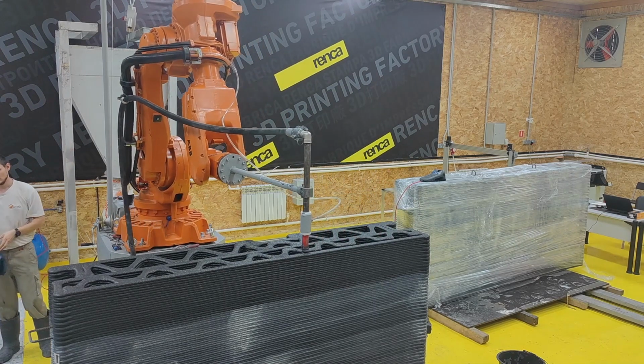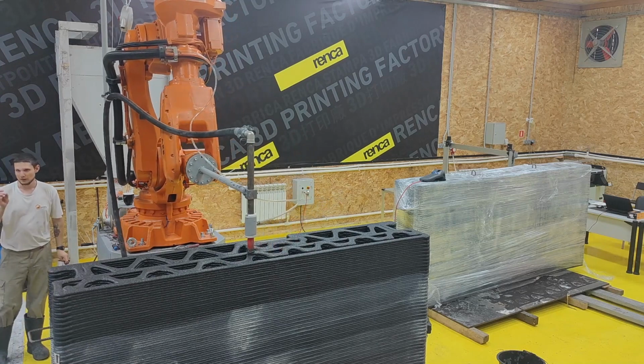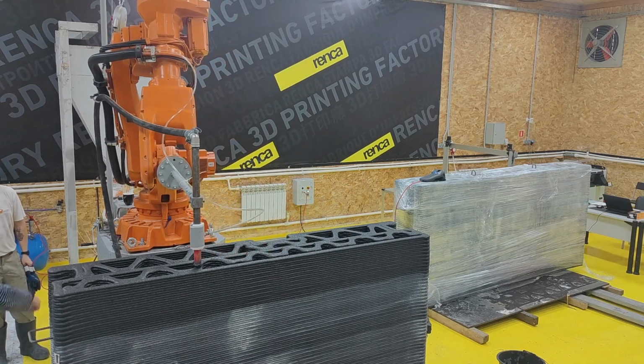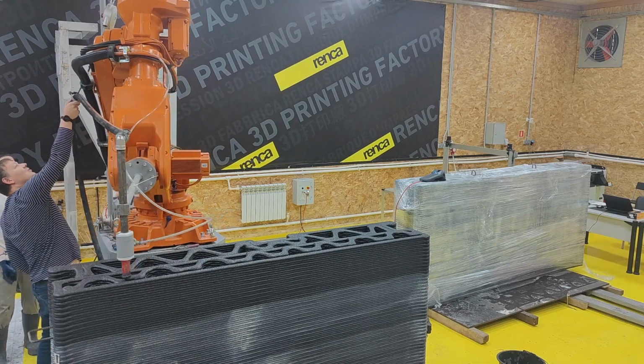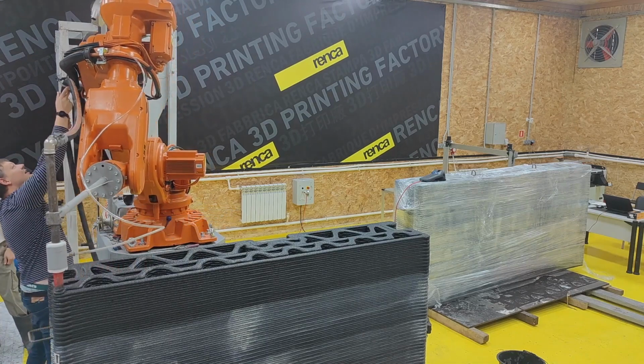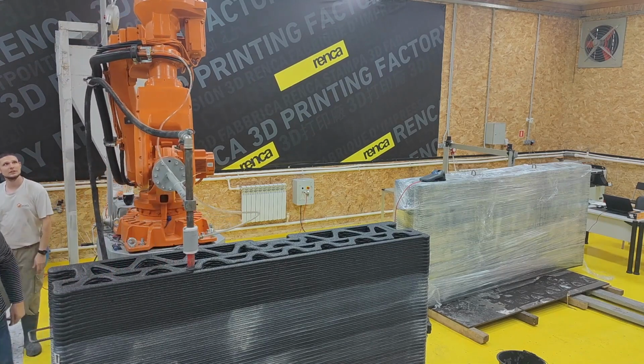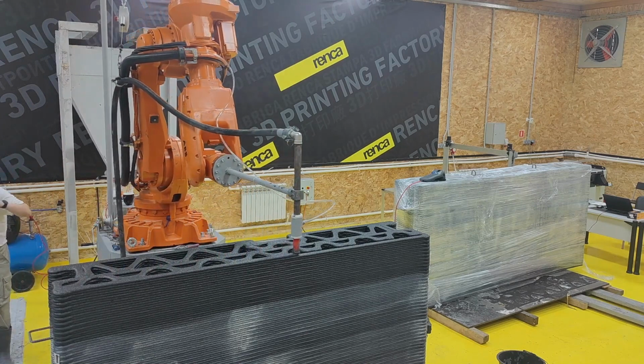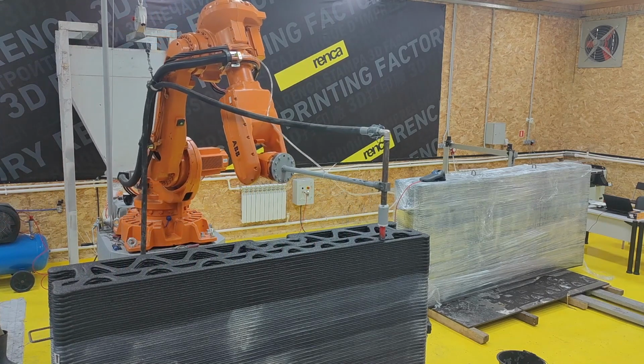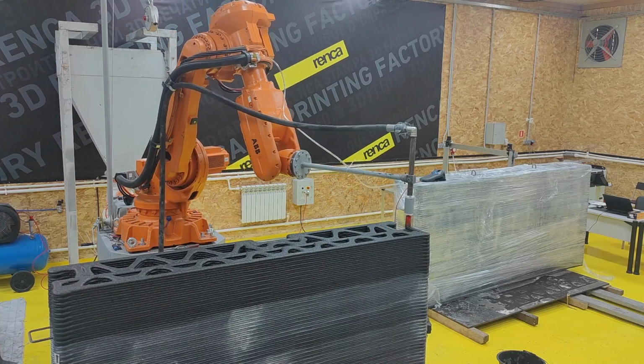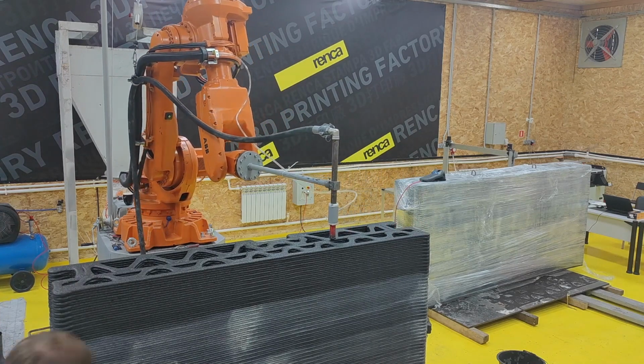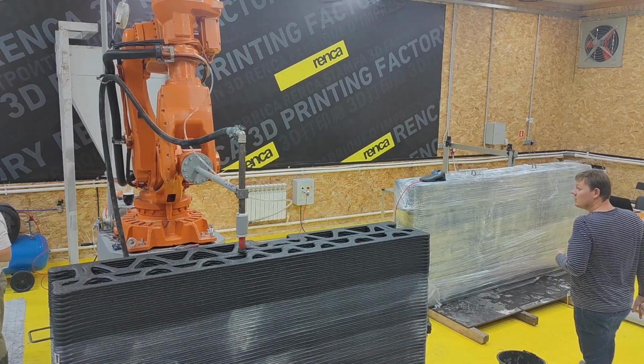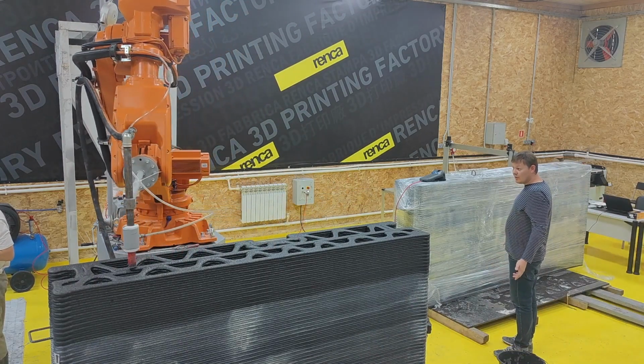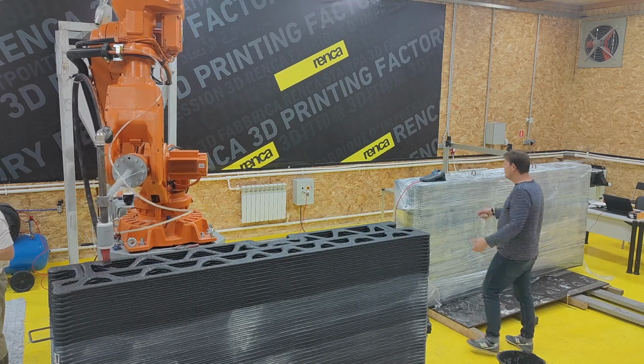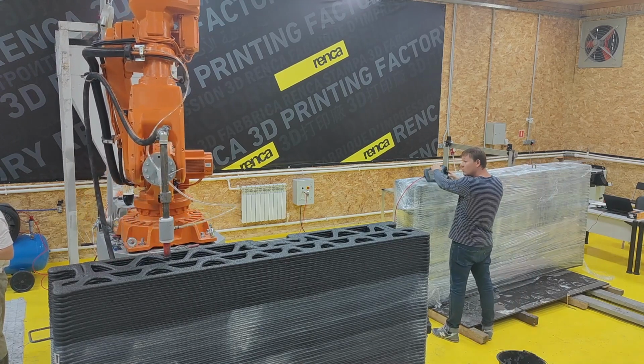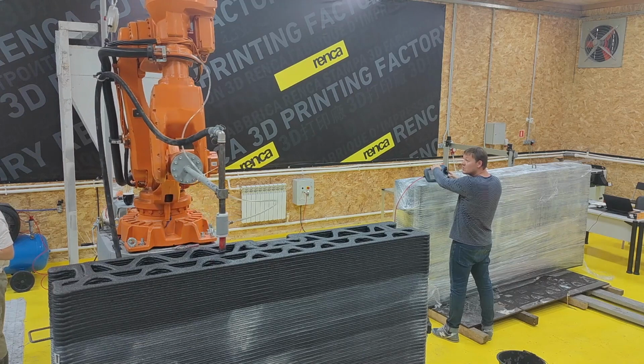International. Is that similar to the one you use? Yeah, this mixer was made by our partner, Alex, in Italy. This is a smaller version, but it's not fully automatic. For 3D printing, there is a complete system with different mixers, which allows us to make geopolymer non-stop. So once the first batch is made, the second is already preparing, and then you have a smooth process, with no interruptions, of feeding your system, feeding your pump.